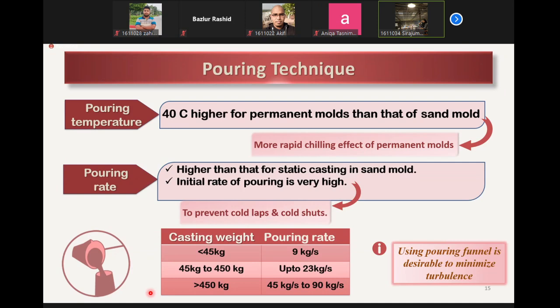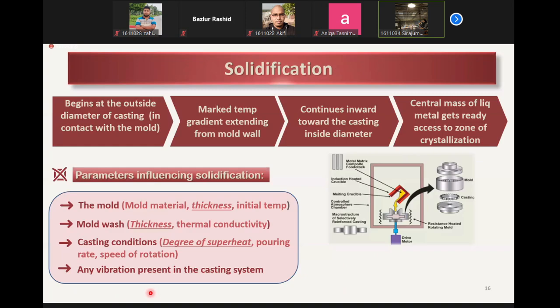Also, it is always good to use a pouring funnel to ensure the entry of molten metal in the direction of mold rotation. It will provide better casting quality by minimizing turbulence. We have already discussed how directional solidification works in this process. Here, heat is only removed through water-cooled mold wall. And these are the parameters which influence solidification. Parameters with greatest effects are mold thickness, mold wash thickness, and degree of superheat. How this affects local solidification condition will be discussed later.